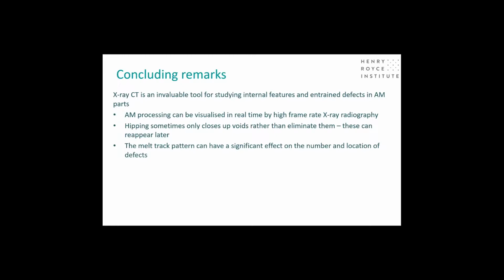The melt track patterns can have very significant effects on the number and the location of defects, and this provides a way of mitigating the effect of defects by ensuring that near surface regions in particular have low defect densities, because it's often the near surface region that is most prone to fatigue cracking. On the whole, fatigue cracks tend to grow from surface breaking defects or defects that are very close to the surface, in preference to those which are internal to the component.